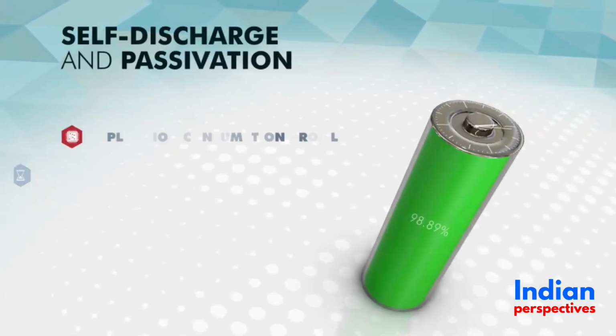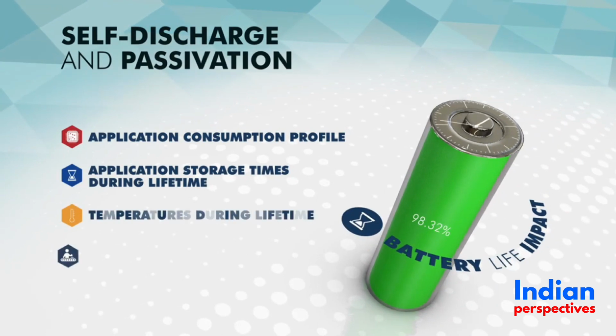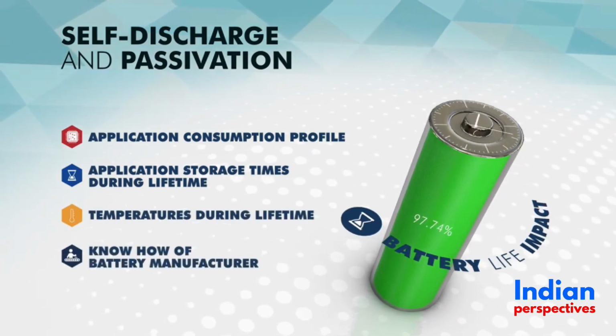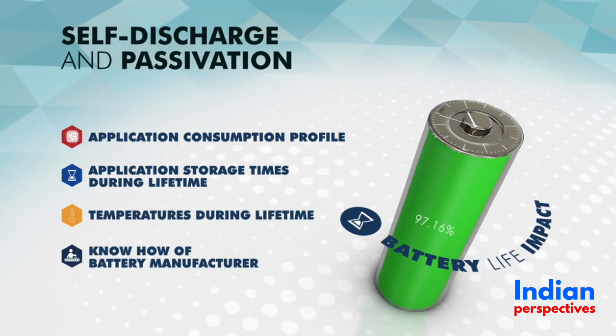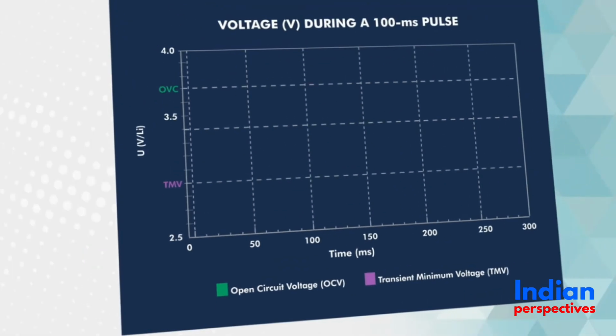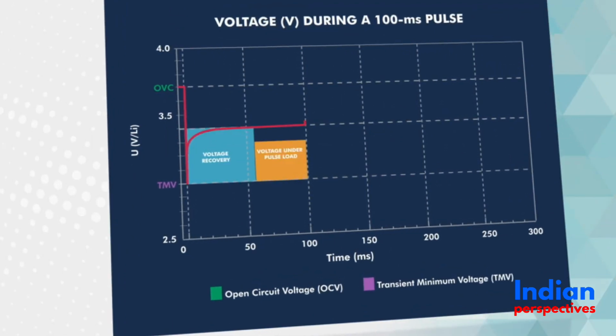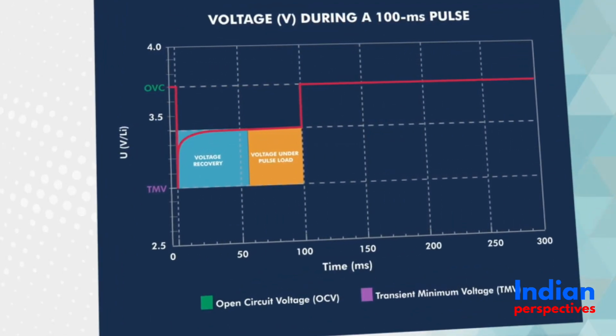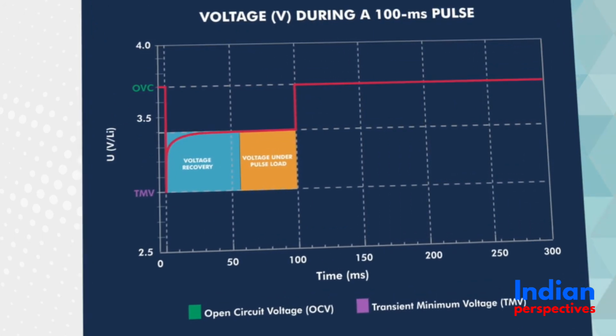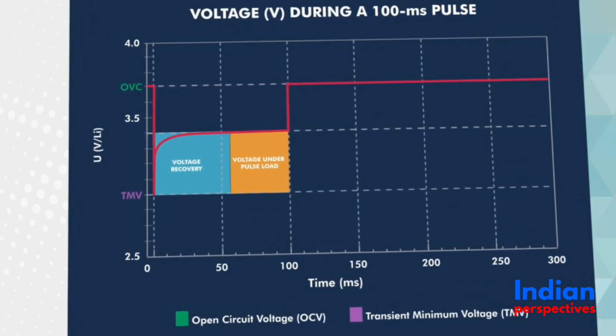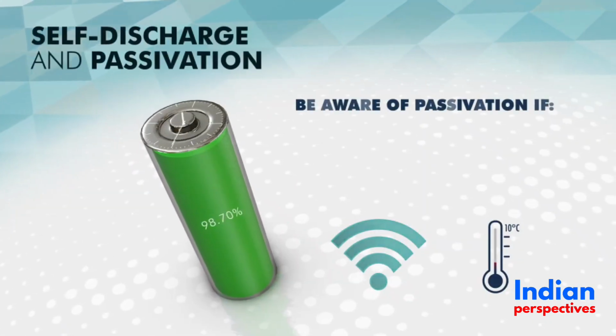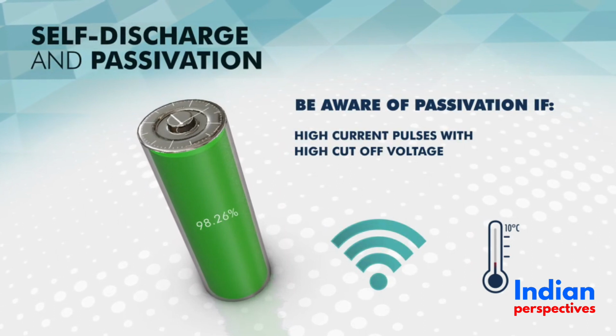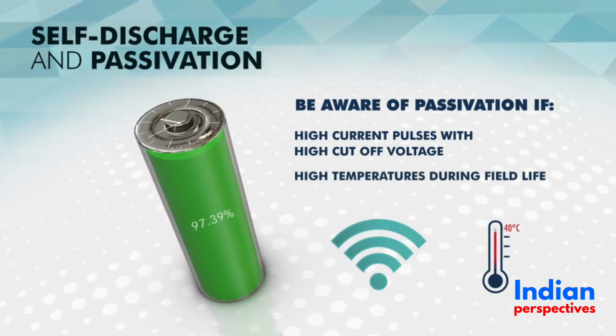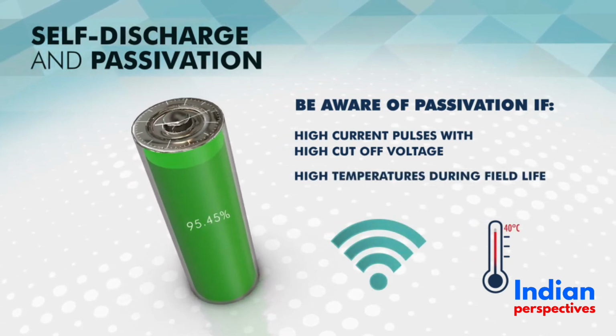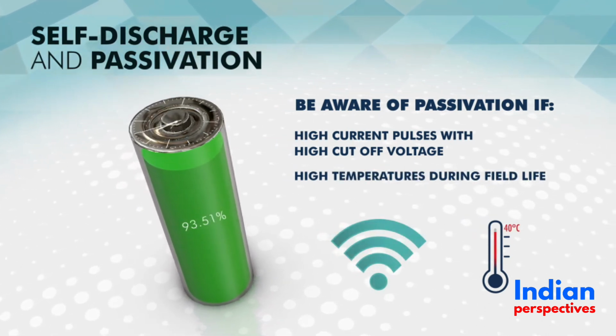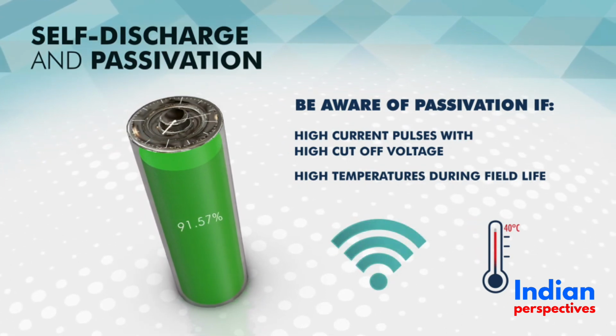Self-discharge and passivation's impact on the battery life is complex to model, and the potential disturbance brought by lithium passivation depends in some part on the application to be served by the batteries. Applications featuring a few milliamperes current draw, voltage cutoff below 2.5 volts, coupled with a few seconds allowable response time, will remain in practice passivation tolerant. Other applications with high current and voltage cutoff, frequent temperature excursions above 40 degrees Celsius, have more chance of experiencing a shorter than expected field life. And this is due to low voltage readings, even though there is remaining energy in the cell.